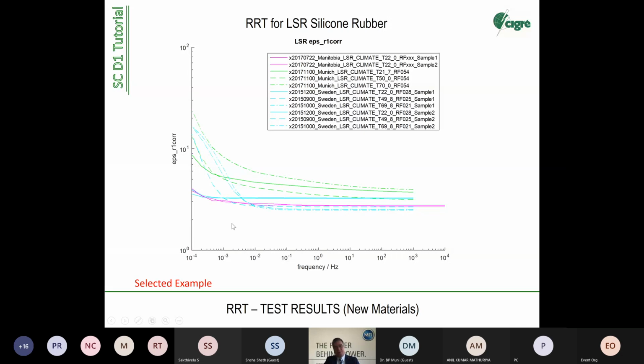What you can also see here are the different laboratories. We see that all show more or less the same tendency, but they have different starting points and different points in the higher frequency range. So the error mechanism is impacting the quality of the test results. Some come very close together. Some in the higher frequency range are good. For example, when we do normal measurements at a technical frequency of 50 Hertz or 60 Hertz, we are in this mid-range. Here we see relatively low scatter. But we should not forget, we have applied the air reference method. With a standard method at 50 Hertz, you will get more accurate results.